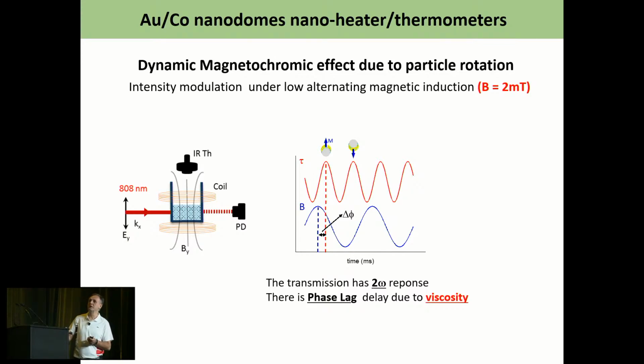But most important is that since the particle is inside the liquid and there is some viscous drag inside the liquid, the particles cannot follow the magnetic field. And there is a phase lag, shown here in this difference, between the frequency of the magnetic field and the optical response. And actually, this phase lag depends on the viscosity of the medium.